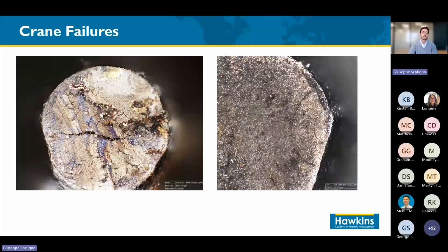Corrosion was involved. In this specific case, we had fatigue corrosion. As you can see here, we have what are known as beach marks, which effectively show the initiation point of your failure, from which, over several cycles of loading and unloading, you can get your wires to fail. And after a single wire fails, more and more of that load is carried by other wires until a number of them fail, and eventually you have a sudden catastrophic failure of your rope.